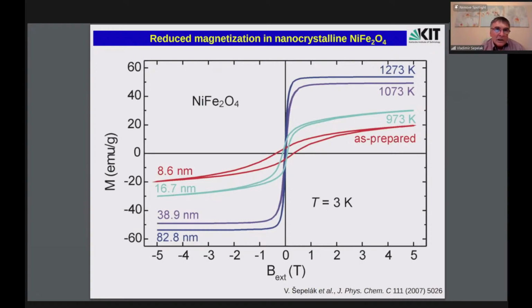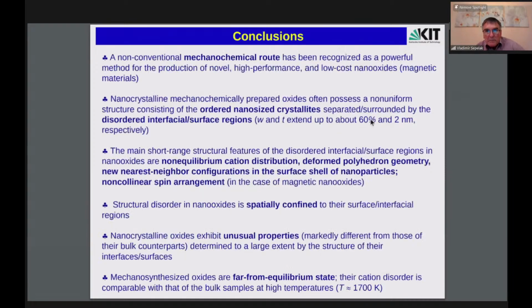That means the non-conventional mechanochemical route to complex nano-oxides has been recognized as a powerful method for production of novel high-performance and low-cost nano-oxides, in this case magnetic materials. Nanocrystalline mechanochemically prepared oxides often possess a non-uniform structure consisting of ordered nano-sized crystallites separated or surrounded by disordered interfacial surface regions, and we were able to determine the volume fraction of these interfaces and thickness, and we observed a value of 60% for the volume fraction of interfaces, and the maximum value was about 2 nanometers for the thickness of the interfacial region.